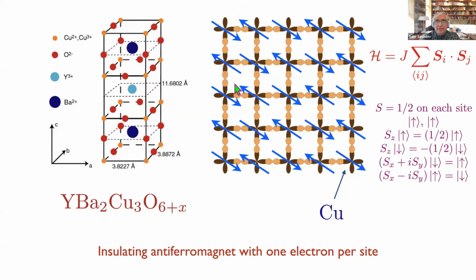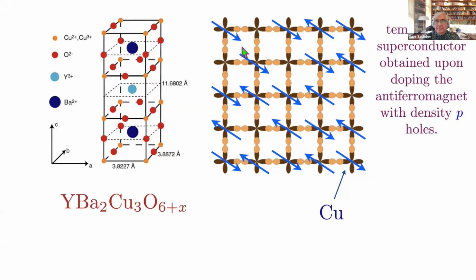So what we are interested in is what happens when you remove a few of these spins, and the density of the spins you're removing from the copper sites is p. I'm going to call this p, and it'll play an important role in everything I'm talking about. So you remove a density p of these holes. And that's when, at some temperatures for certain values of p, you get this remarkable phenomenon of high temperature superconductivity.